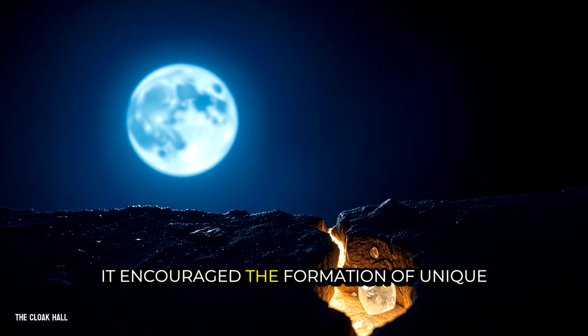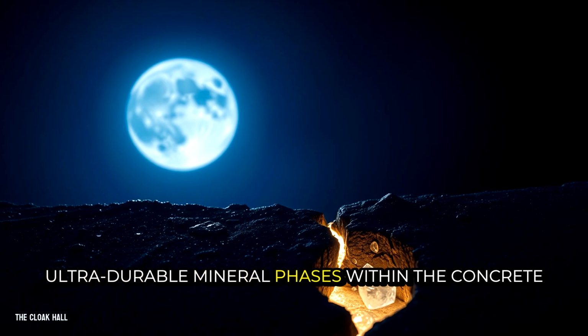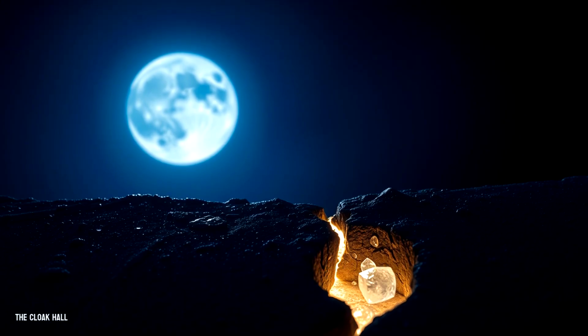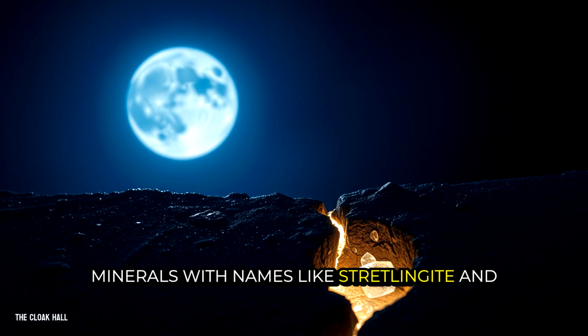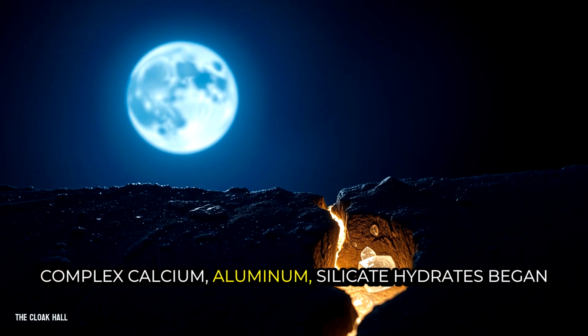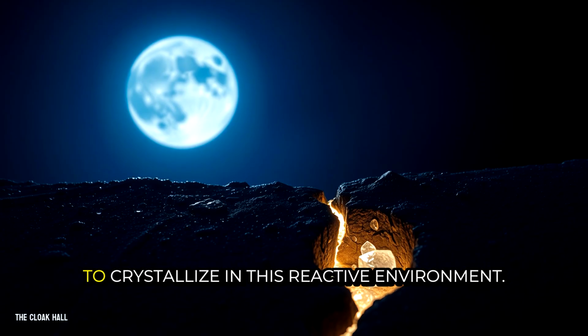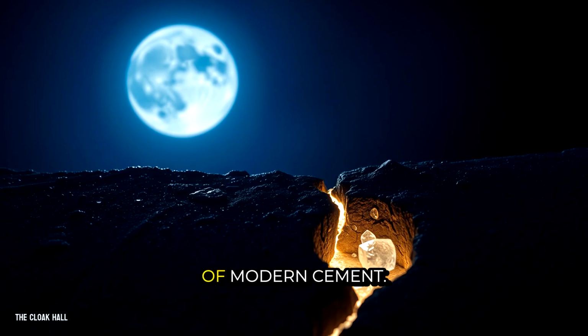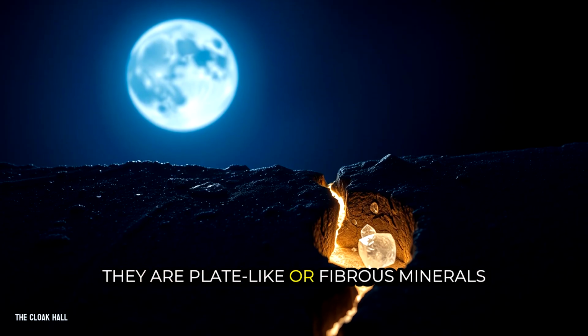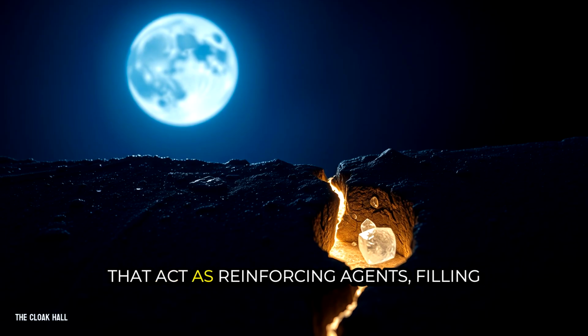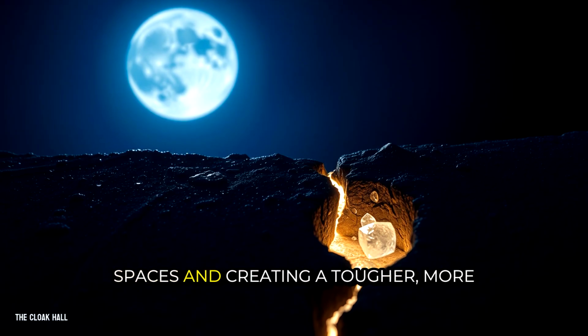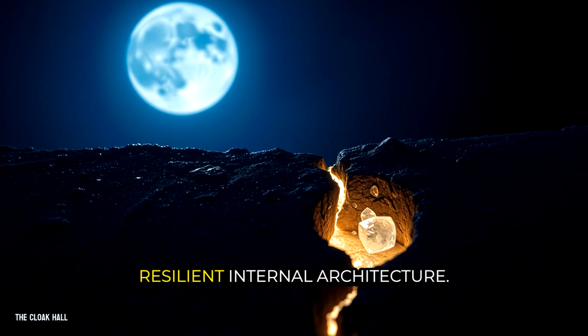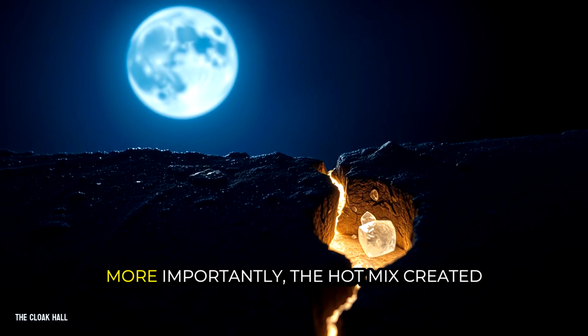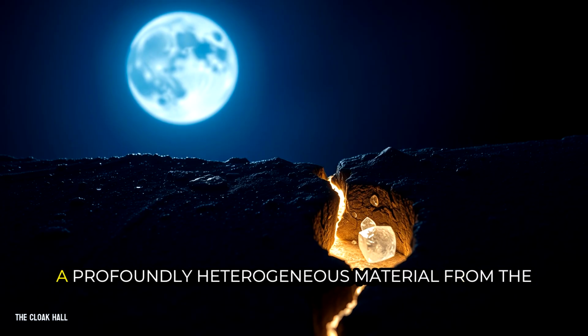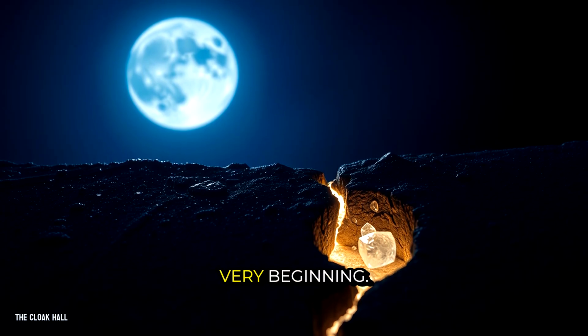It encouraged the formation of unique, ultra-durable mineral phases within the concrete as it cured. Minerals with names like strätlingite and complex calcium-silicate-hydrates began to crystallize in this reactive environment. These are not the brittle crystals of modern cement. They are plate-like or fibrous minerals that act as reinforcing agents, filling spaces and creating a tougher, more resilient internal architecture. More importantly, the hot mix created a profoundly heterogeneous material from the very beginning.